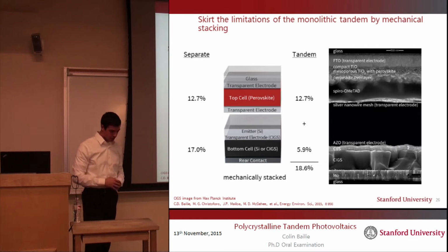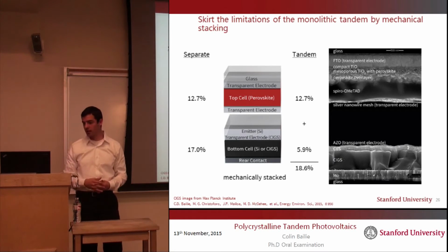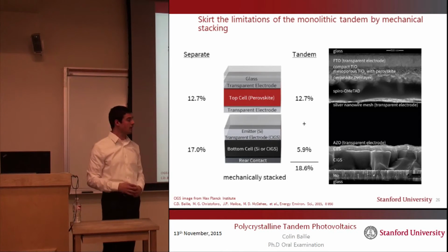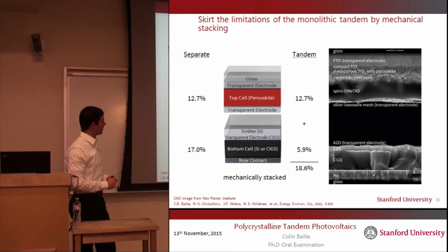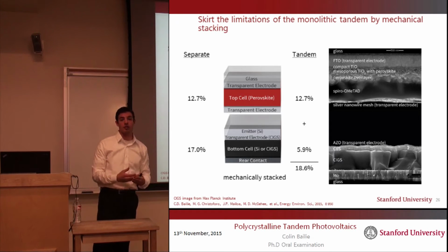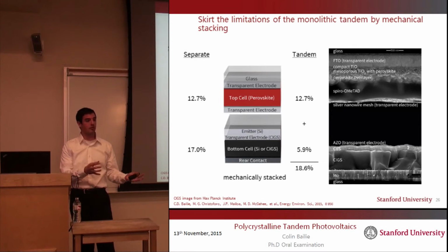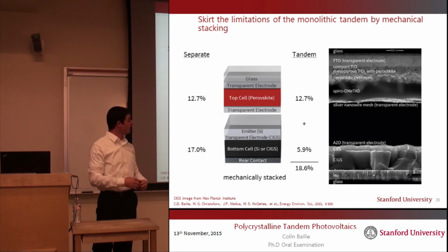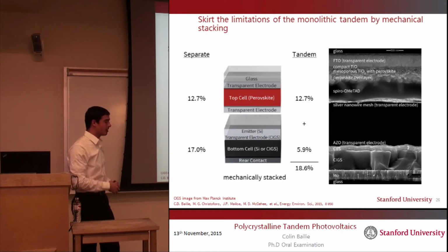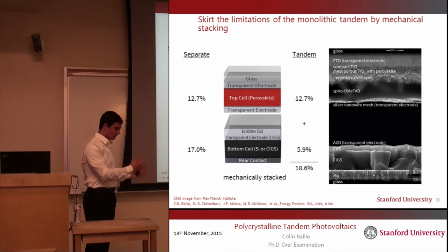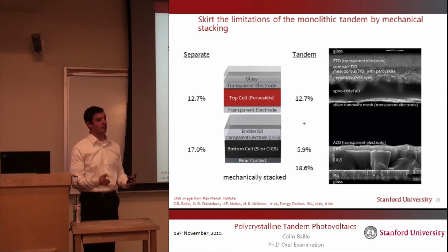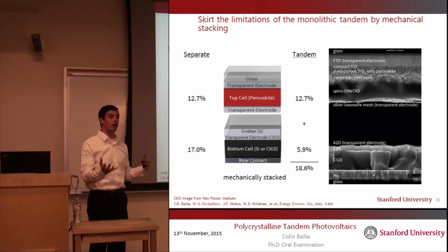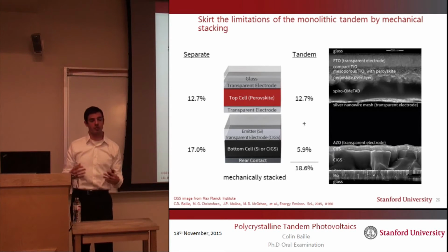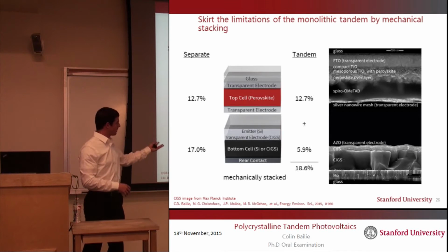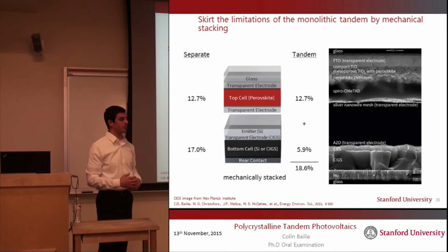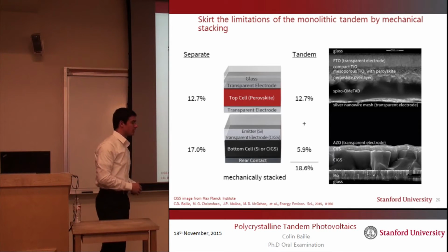And so here is the first generation of perovskite mechanically stacked tandems that we made, where we used a semi-transparent perovskite cell that was about 12.7%. And semi-transparent meaning that while it absorbed the visible light, it was transparent to the infrared light, which then we stacked on top of the 17% silicon cell. 17% efficiency in silicon being a representative number for what you could go out and buy if you purchased a silicon module from a commercial vendor. And when we stacked the two together, we got about an 18.5% tandem, representing a moderate improvement over the silicon cell by itself.